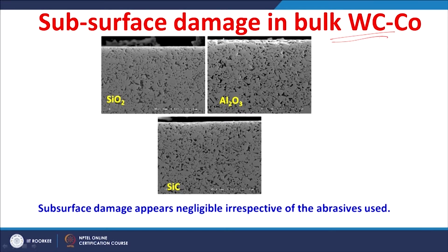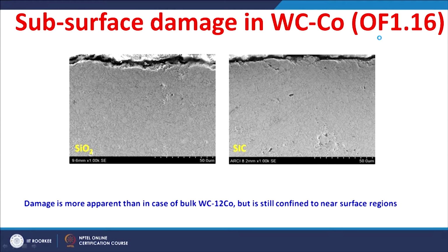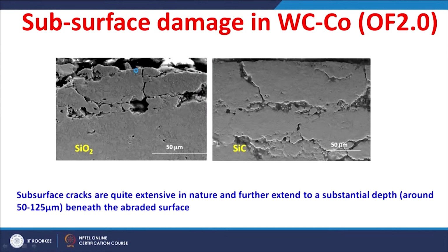This damage appears to be negligible irrespective of the hardness of the abrasive used, but the subsurface damage is more apparent in the tungsten carbide cobalt coating, though it is still confined to very small regions underneath the surface. Both in the case of silicon oxide abrasive and silicon carbide abrasive. But if you see the damage occurring for the coatings done with the higher oxygen to fuel ratio of 2.0, the subsurface damage is extensive. You can see the cracking is extensive, that extends to a substantial depth.